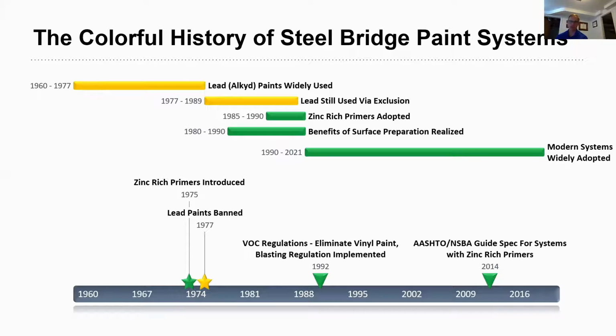One thing I forgot to mention there is down at the bottom, in approximately the early 90s, there were some VOC regulations, and VOC stands for volatile organic compound. It's a compound, or a solvent, that gets released into the air as the paint dries. That was an EPA regulation, and that definitely had some influence on the modern corrosion protection systems today. So the combination of blasting as well as zinc-rich primers really changed paint systems in approximately the 90s and leads us to currently what we have today for paint systems.